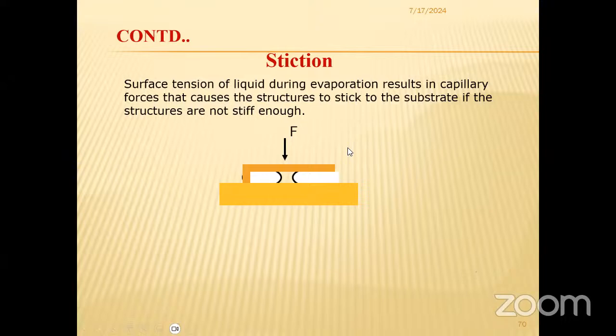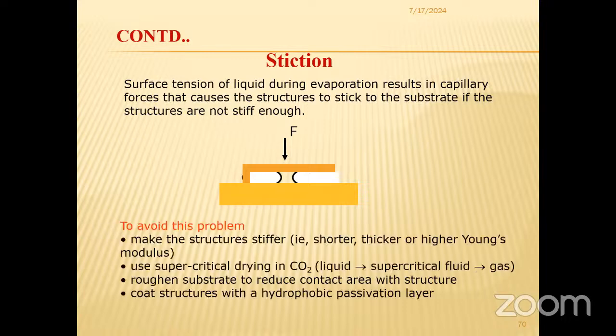So there is a stiction problem in surface micromachining. That is, the gap between the micro cantilever and the silicon is very, very small. So if you wash it with water or with any chemical, there is a problem of stiction. That means chemical molecules may get stuck between the structure and the silicon, and it is not an easy task to remove the molecule that is stuck in between the two layers. It is not easy to remove it.